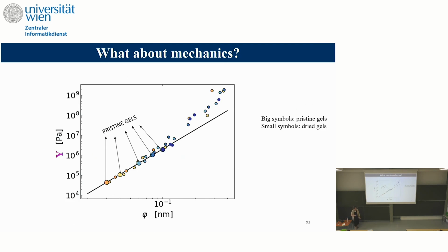So we have this curve, okay? This is a pristine gel, so the gel before drying, okay? Different volume fraction, from 2 to 10. The higher the volume fraction, the higher the elastic modulus. It's more or less what Mehdi showed, that you have this power law here. It's 3 point something, that you observe in many different conditions.